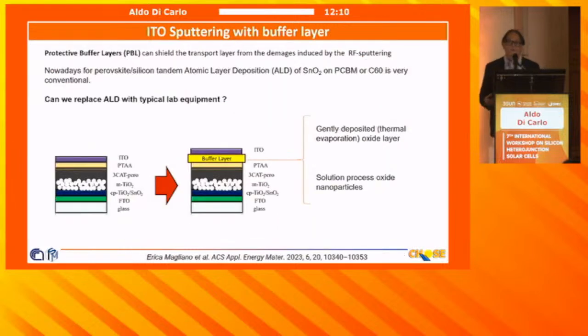But the usual technique people use, and we have seen also before, is ALD, atomic layer deposition. The point is that ALD could be quite expensive equipment, and it's quite complex to run. So the idea is, can we replace ALD with a simpler solution so that everywhere in the world people can do tandem and contribute to its development? The idea is to have a buffer layer, and the buffer layer could be deposited in two simple ways. One is thermal evaporation of the buffer layer, so you protect the layer from the sputtering via the buffer layer, or you can use solution-processed nanoparticles. I will show you these two solutions.